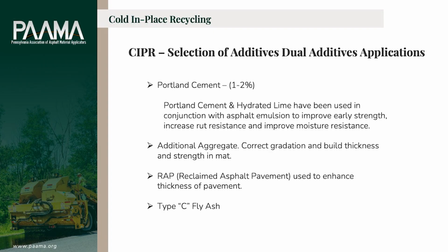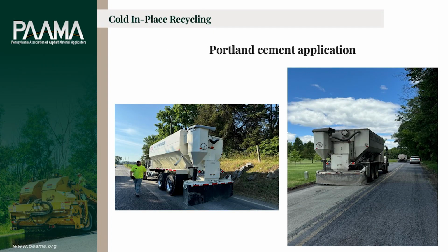Well, what does that do for us? The Portland cement acts in several ways. What it does is it becomes a slurry mix, so it's filling some air voids. It's a catalyst. We haven't got to wait. Normally a cold in place recycle road, you're going to sit there and wait for 2 weeks for it to cure out. You're going to allow traffic to run on it, but it still takes that much time for the moisture, because an emulsified asphalt is about 65% asphalt cement, about 35% water. We need that water to get out of that mat before we overlay it and lock the water in place.